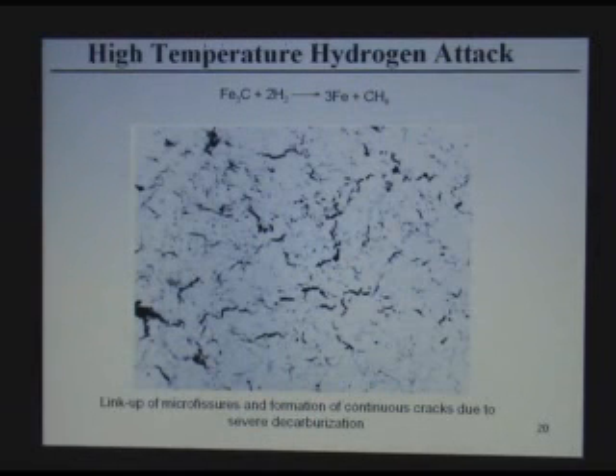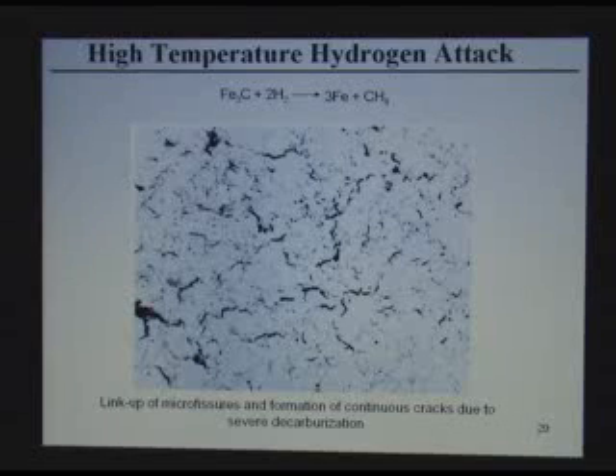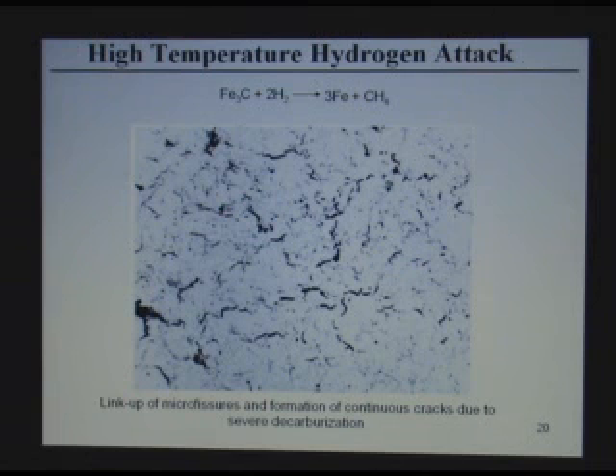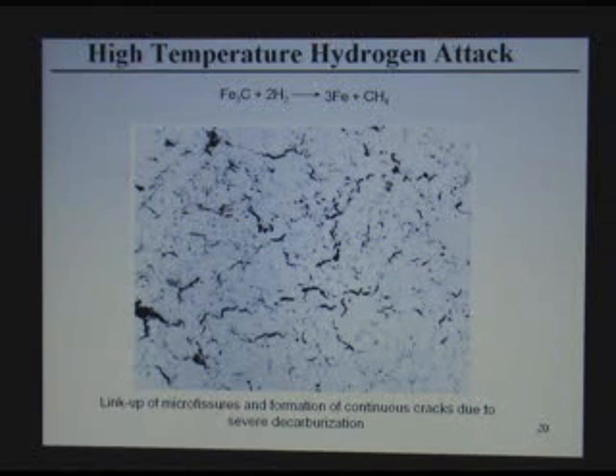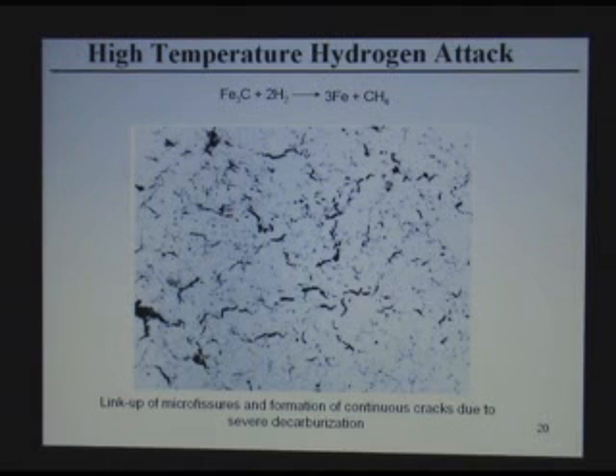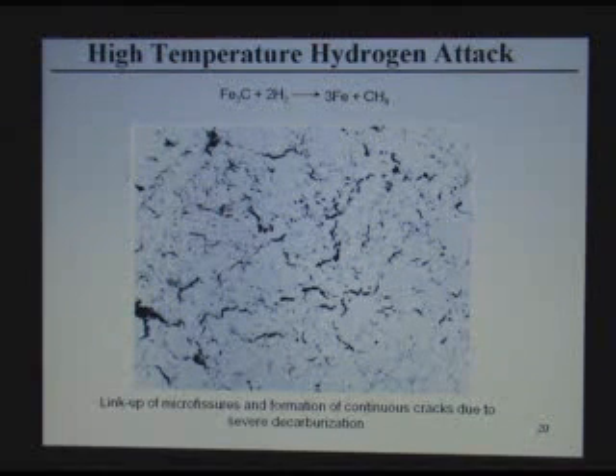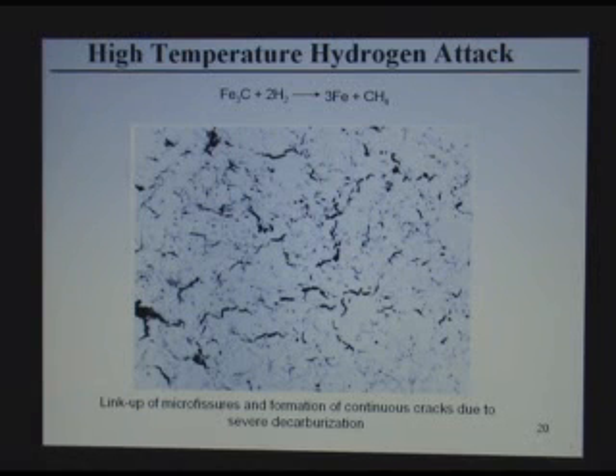This slide came in prematurely, but this is an example of high temperature corrosion attack. Here, high temperature hydrogen reacts with the iron carbides in the steel and forms methane inside the metal and leaves iron without carbon. As the pressure builds up inside the crystal, it starts breaking, and you see the fissures inside the metal. This is what they call hydrogen attack.